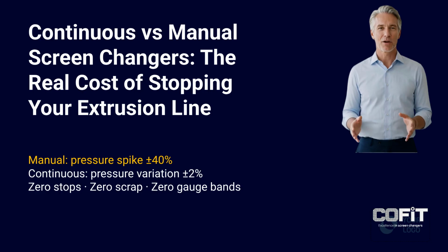In a continuous belt design used for high-contamination recycling applications, a moving belt of metal mesh advances fresh filtration area automatically as the loaded section exits. The belt advances when differential pressure reaches the set threshold. The line never stops for the belt advancement. In both cases, the screen management event that previously cost 15 to 45 minutes of production becomes invisible to the process.